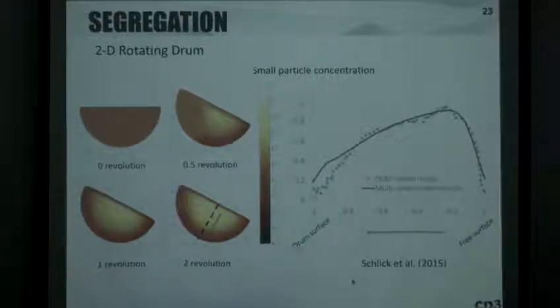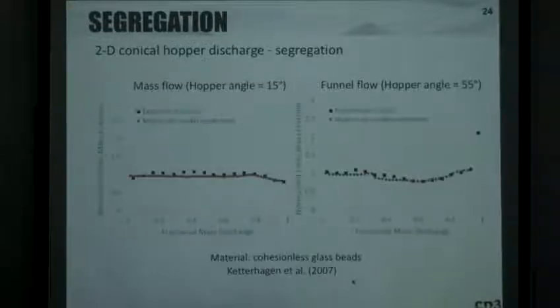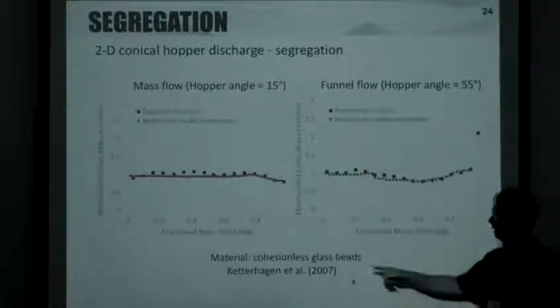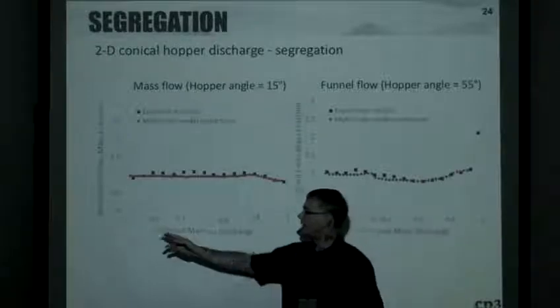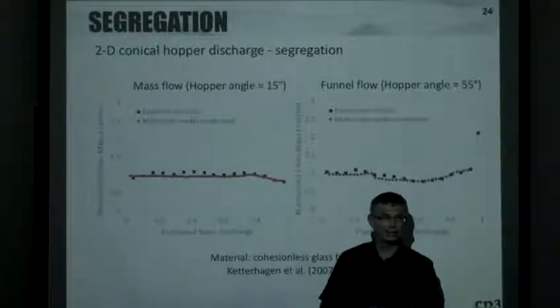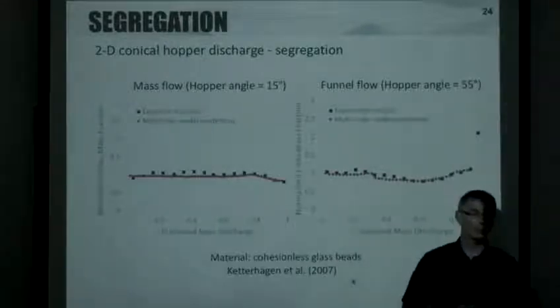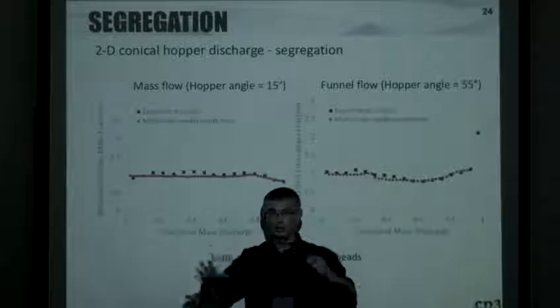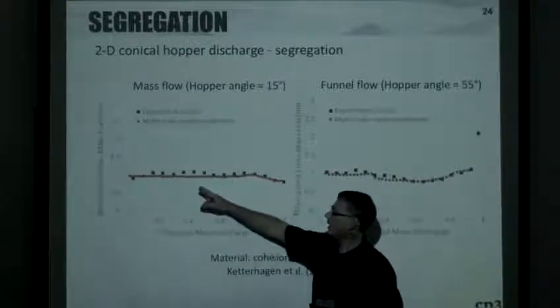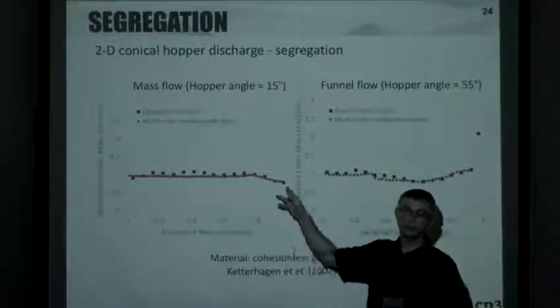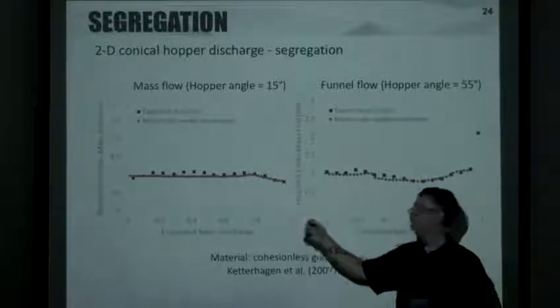Pretty good. And then we also did the hopper discharge, comparing against the experimental work of Bill Ketterhagen, where he used glass beads. This is a discharging hopper. What we did is collect samples at the exit of the hopper and look at what fraction, by mass, is the fines or the small particles. That's the vertical axis. What you see is that the particles start pretty well mixed, staying at a value of 1, which is what you expect if it's well mixed. And then it drops down a bit, which means that it's primarily coarse particles coming out at the very end. That was for mass flow. This is for funnel flow.